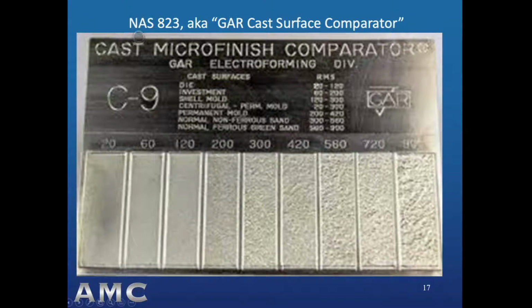This is the National Aerospace Standard 823, also known as the GAR Cast Surface Comparator. Basically, these surfaces are replicated from actual casting surfaces. This is the best way to evaluate a casting surface because you can hold the plate up against the light at different angles. You can touch it, you can touch the casting, and you can make a visual and tactile comparison of surface finish most effectively this way.